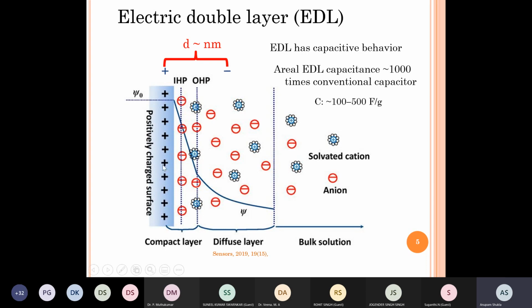Okay. However, if I place a solid and connect this solid to some electric supply so that this solid attains a positive or a negative charge on its surface, then the liquid responds in a way to compensate for the excess charge that it sees on the surface of the solid. And as a result, some of the region near the solid surface becomes charged. So the liquid side of the system close to the solid surface also becomes charged. And of course, there are different layers of charge, but essentially the idea is that some part of the liquid also becomes charged. So essentially now what you have, to be specific here, is a positive charge on the solid side, and there is a negative charge on the liquid side.